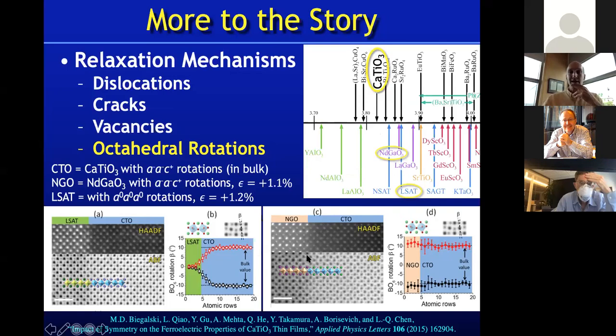If we contrast that to what happens in going from neodymium gallate to calcium titanate, neodymium gallate has the same space group 62, Pnma, as calcium titanate. So the octahedral rotation pattern of neodymium gallate is the same as the octahedral rotation pattern of calcium titanate. So although the pseudo-cubic lattice constant of neodymium gallate is almost identical to that of LSAT, notice this huge difference in how these octahedral rotations evolve.